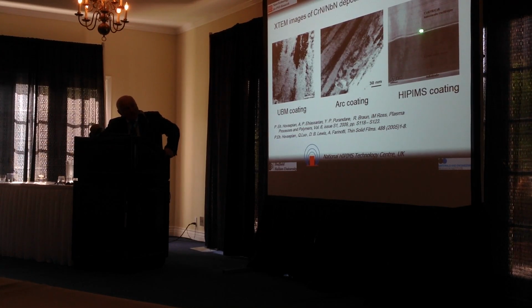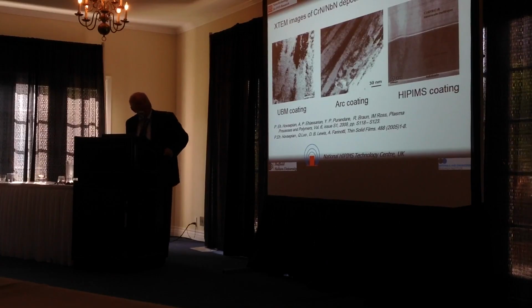With HIPIMS, your layers are really with sharp interfaces. They're not wavy. You don't have the defects in the arc. So basically, this structure is winning from this point of view compared to state-of-the-art technologies.